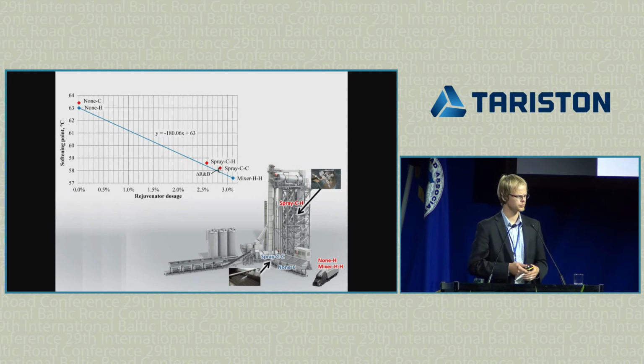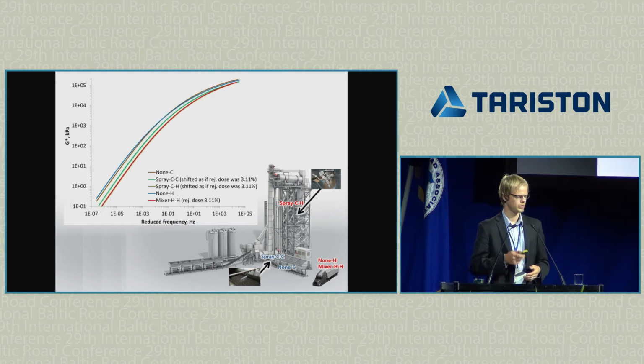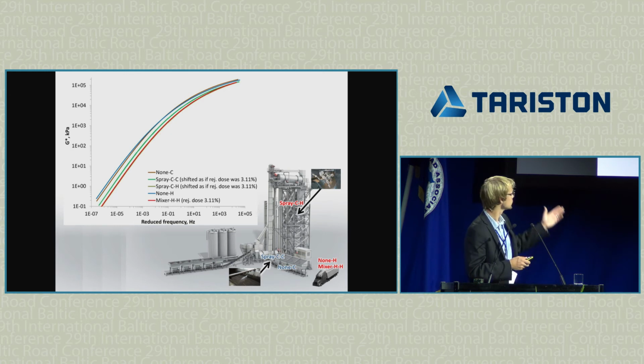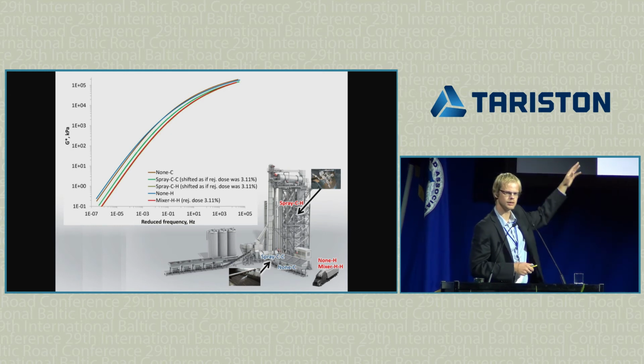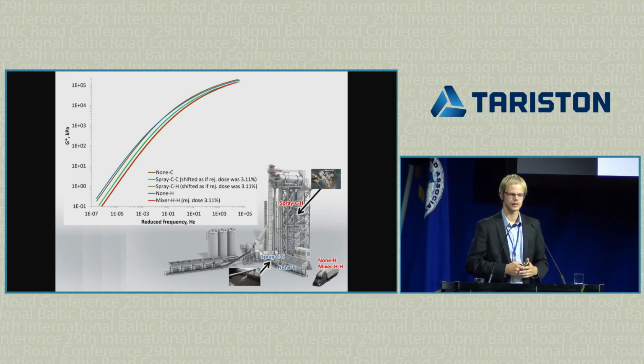Next, softening point, and basically the same idea. Again, the results are almost on the trend line. Next, we used the dynamic shear rheometer to build a master curve, which is basically the stiffness and elasticity ratio at different frequencies of the reclaimed asphalt binder. And of course, the stiffer the material, the higher the master curve would be in this graph. We see that for the reclaimed asphalt binder without any rejuvenator, the lines are higher up. When we have added the rejuvenator, they are lowering, but we again see that they are lowering to the same extent whether we added the rejuvenator to the hot or to the cold binder or RAP.